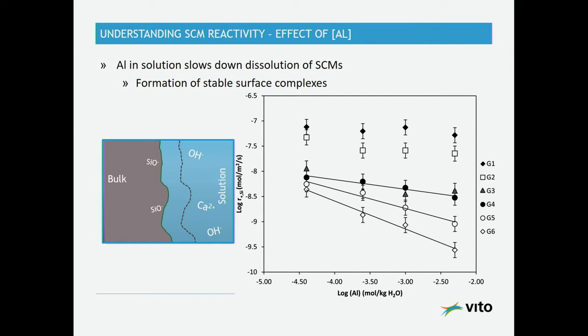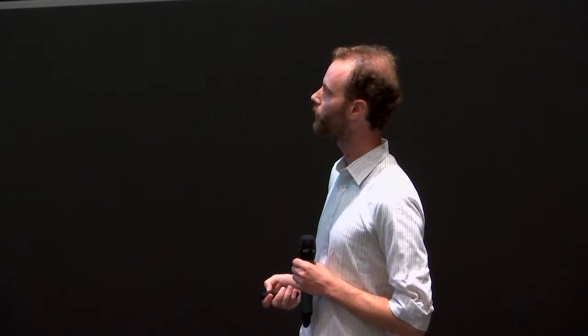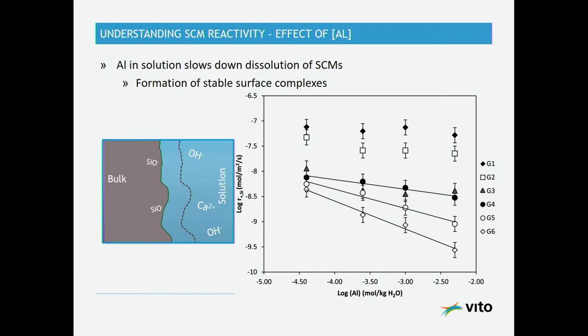So finally, in also looking at what factors really can affect the SCM reactivity, one can also look at aluminum. And we actually really see that aluminum in solution slows down the dissolution of the SCMs, especially for silica-rich SCMs. So for the G6, G4 type glasses, we see that when we increase the amount of aluminum in the solution, we really decrease by, in this case, even more than an order of magnitude, the dissolution rate.